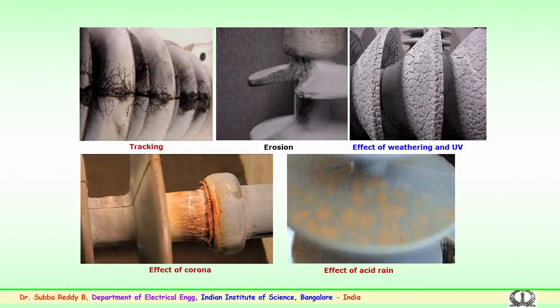Some of the failures which have happened, from the literature, have been presented here. This is not the presently available information; it covers a period of time since the inception of this technology. Several failures or problems are reported here. It could be tracking, as you can see here, of the insulator over a period of time. This could be because of continuous surface degradation where the electric arc or current starts conducting and flashover happens over the surface. This leads to the failure of the entire string, and replacement is needed.